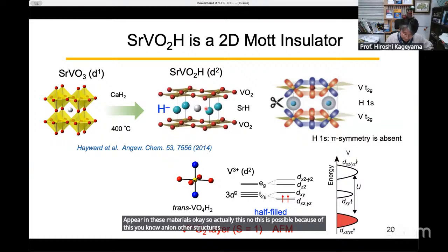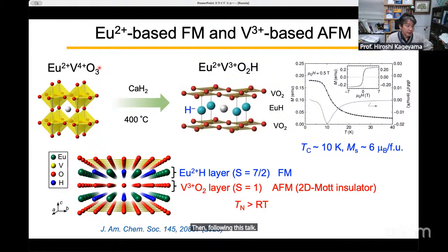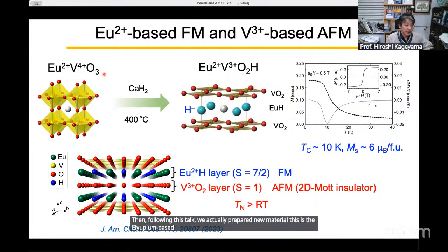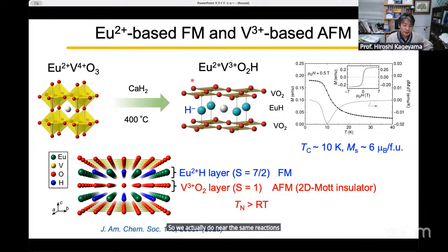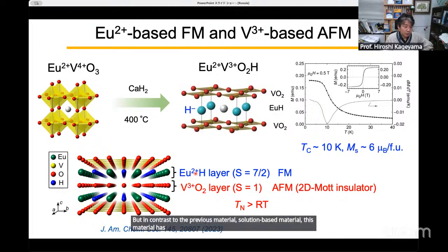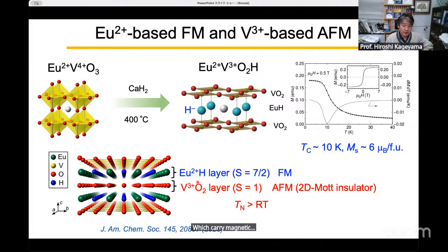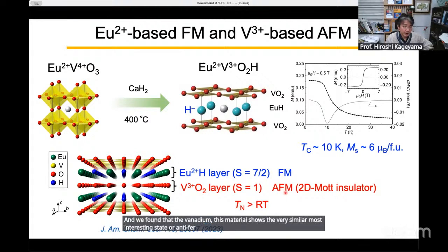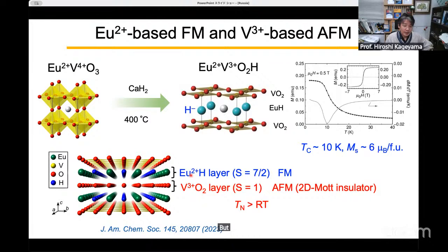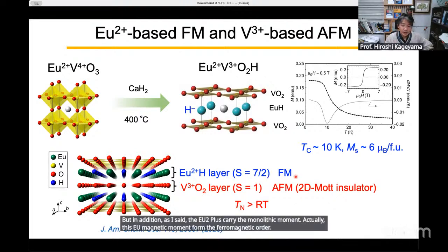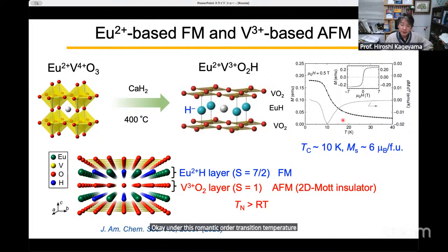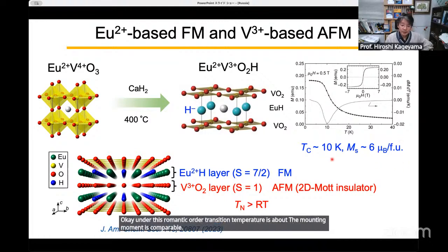Following this work, we prepared a new material, the europium-based vanadium oxide. We did nearly the same reactions and obtained isostructural materials. But in contrast to the previous strontium-based material, this material has Eu2+, which carries a magnetic moment of S equal to 7/2. We found that this material shows a very similar Mott insulating state or antiferromagnetic ordering state based on vanadium. In addition, the Eu2+ moments form a ferromagnetic order, and this ferromagnetic transition temperature is about 10 Kelvin. The magnetic moment is comparable with our expectations.